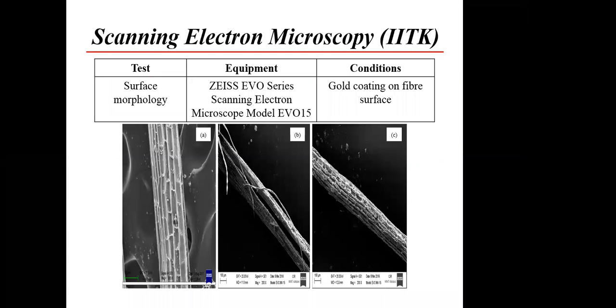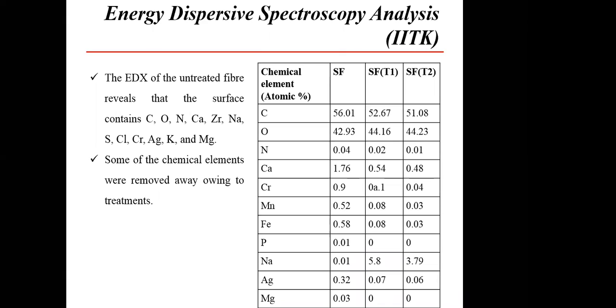Scanning electron microscopy is done at IIT Kanpur. Figure A shows some fiber cells with impurities, and after sodium bicarbonate treatment we get fibrillation. Because of fibrillation, the surface gets rough. If the surface is rough, that means more bonding takes place. Good interfacial bonding between fiber and matrix will take place after treatment or coating. EDX analysis is also done at Kanpur.